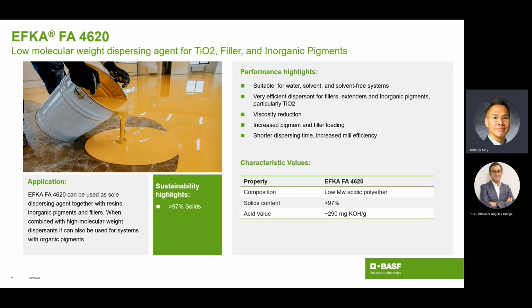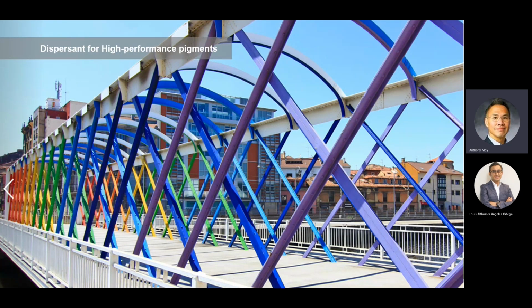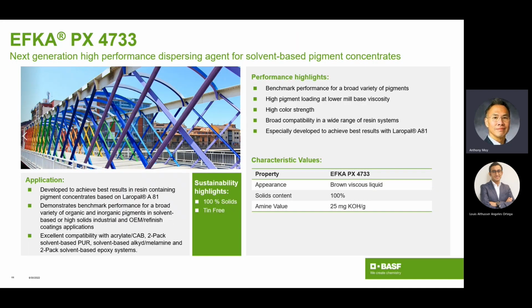The second category of dispersing agent I would recommend is for high performance pigments. What are high performance pigments? These are the pigments that are primarily used for their aesthetic effects, things like carbon black, phthalo blues and greens, cyano reds, and so forth. Pigments that typically have fairly small particle size and large surface areas, making them very difficult to disperse, we would recommend one of our high performance dispersing agents, and that is EFKA PX 4733. It is 100% solids as well as being tin free.